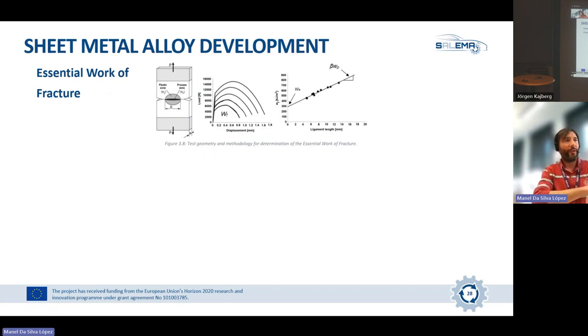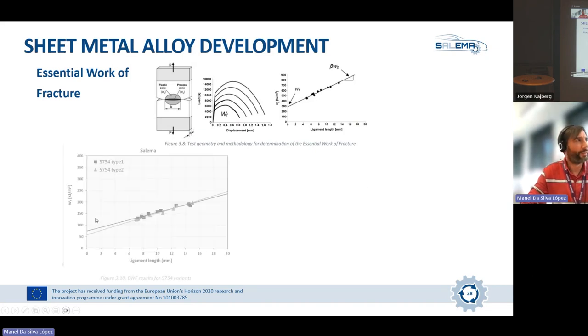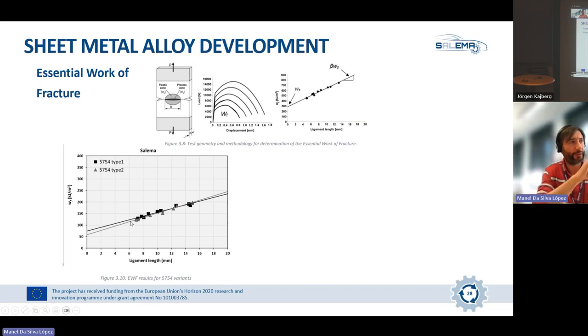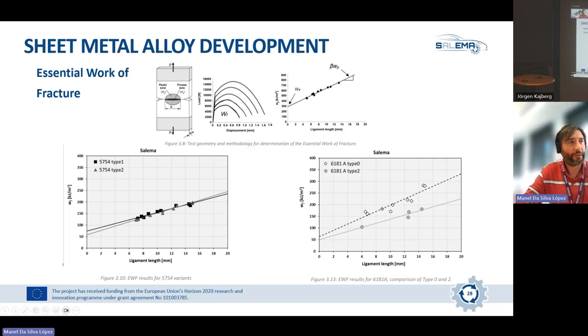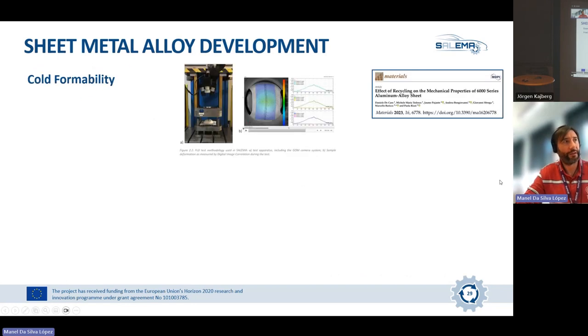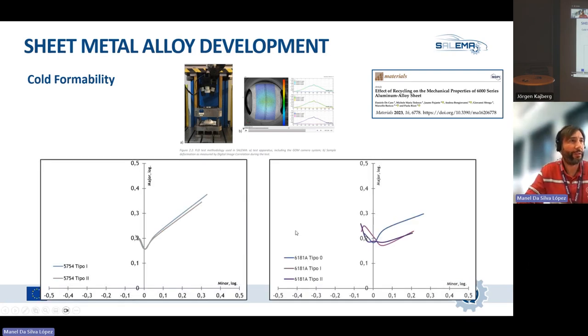But if we look at other properties, such as the essential work of fracture that was probably presented by Sergi earlier this morning, we observed that for the 5754 there was almost no difference. There was a cloud of points that could perfectly be from the same material. But on the 6181, we had 2 different behaviors, which were related, in formability, to differences in the formability test curves. Here on the right, you can see clearly how types 1 and 2 for 6181 decrease the formability.